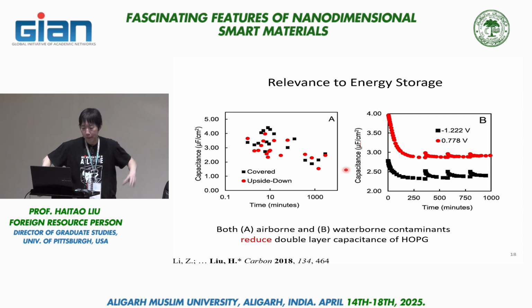Okay. Because the energy stored within the double layer structure, the larger the capacitance, the higher the energy storage density you can achieve. So what we did here is on the left, we measure the double layer capacitance of graphite basal plane.